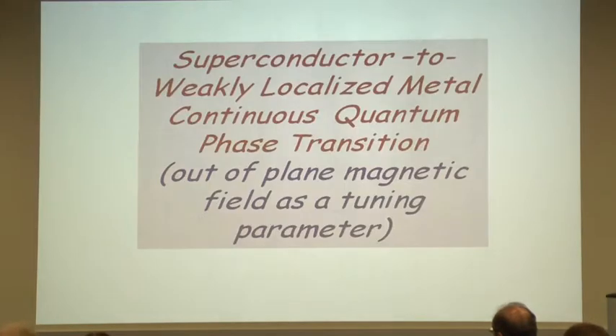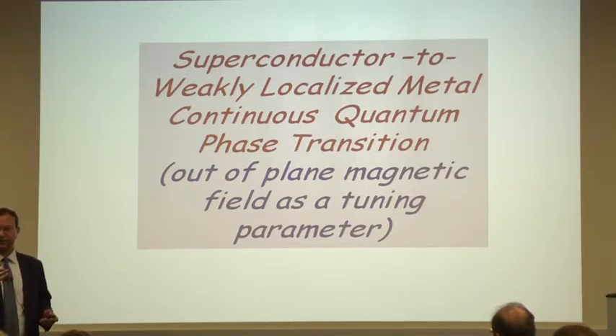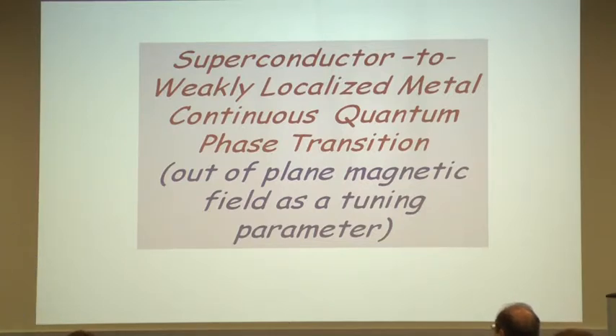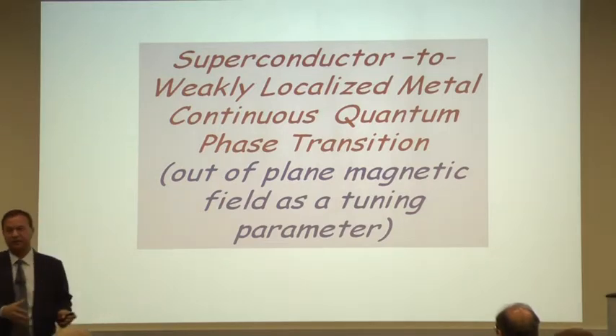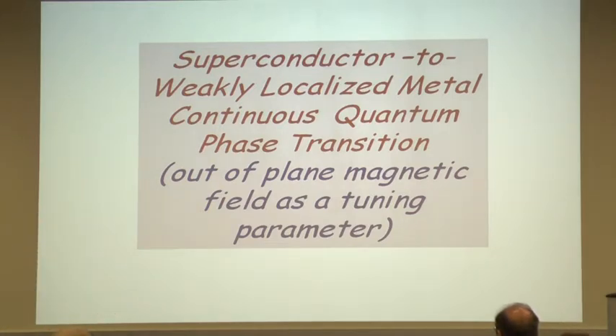So this two-band picture sort of explains why there is a curvature in the Hall resistance at very high positive gate voltage. Now I'll talk about the superconductor to weakly localized metal continuous quantum phase transition in the system, because it's a very, very attractive system in a way, because you can tune the Coulomb interaction between the carriers by simply changing the carrier concentration through a gate voltage. And you can also change the interaction between the carriers by applying a perpendicular magnetic field. So you can push the material from the superconducting state to a non-superconducting state by using two variables, the carrier concentration and magnetic field.